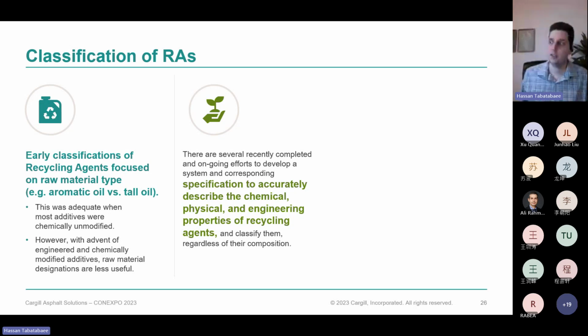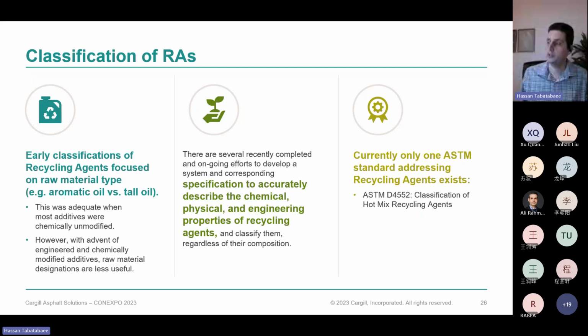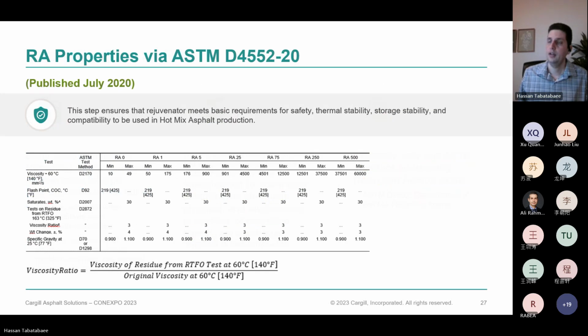There are a number of different ways that these are being looked at, but one of the most commonly used today is ASTM D4552. This standard is a simple two-page standard. It has a table that some of you will probably find very familiar. It essentially describes recycling agents as a function of their viscosity, and has basic requirements for flash point, amount of saturates, and the aging resistance of the material.